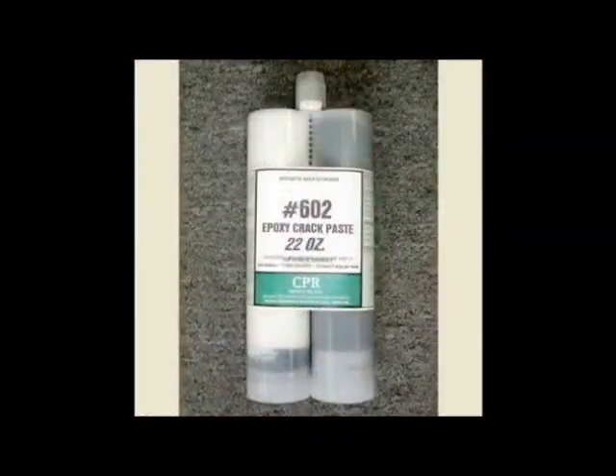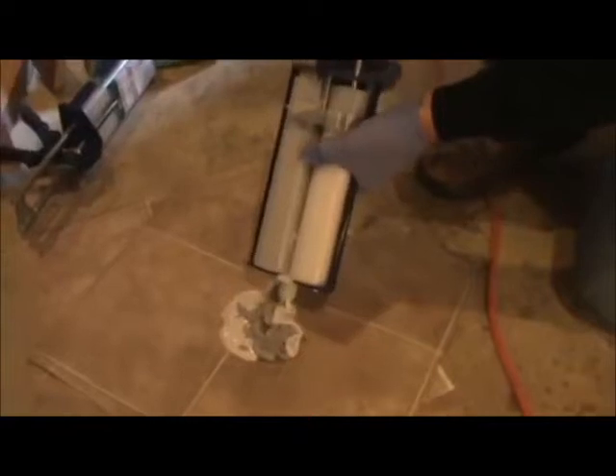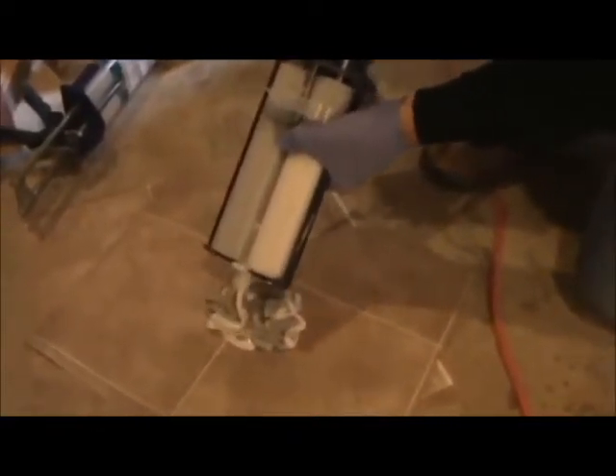Step two, using epoxy crack paste, you're going to attach surface mount ports over the crack. Because number 602 crack paste has only a 7 to 10 minute pot life, you will want to mix a smaller batch than what Mike is mixing here. He's done epoxy injection every day for the last 15 years.